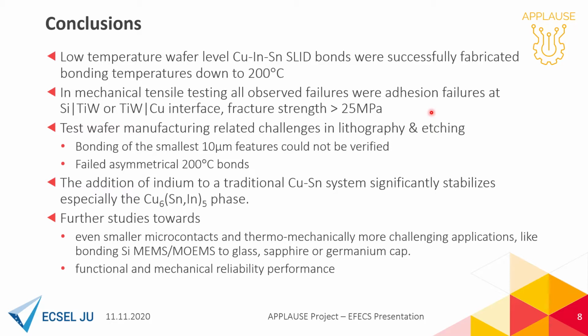The addition of indium to the traditional copper-tin system seems to significantly stabilize the microstructure, especially copper-6 (tin, indium)-5 phase. Since these preliminary results are very promising, the further studies will be towards even smaller microcontacts and thermomechanically more challenging applications like bonding silicon MEMS or MOEMS components to glass, sapphire or germanium caps. In addition, functional and mechanical reliability performance needs to be verified.